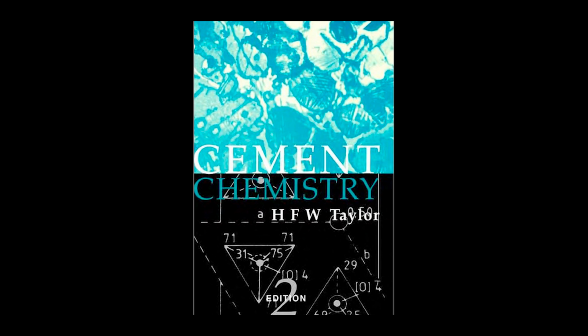This rapid, uncontrolled crystal growth destroys the workability and results in poor final strength because the internal structure is damaged right at the beginning. Okay, so that's the bad one. What's false set? False set is more of a physical or a mechanical problem. You get rapid stiffening, but crucially, there is no abnormal heat evolution, and the plasticity is regained simply by continuing to mix the material. So you can just mix through it. You can mix right through it. The most common cause is during the cement grinding process. The heat of grinding partially dehydrates the gypsum, forming hemihydrate.